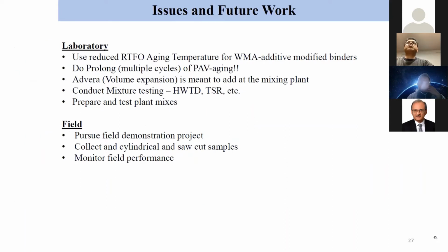In terms of laboratory work, we had consulted the manufacturer. They gave some ideas, but because of the time, we could not do that. For example, RTFO aging, we should probably have done at a lower temperature than the ASTM procedure. So that is one thing that we can do in the future.